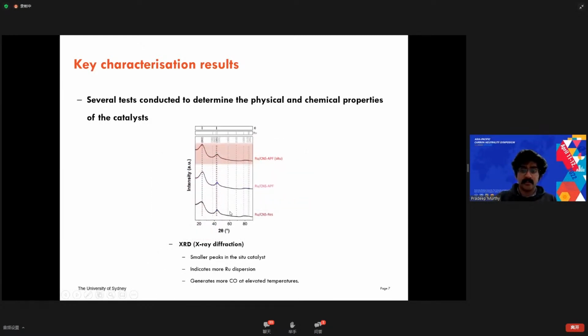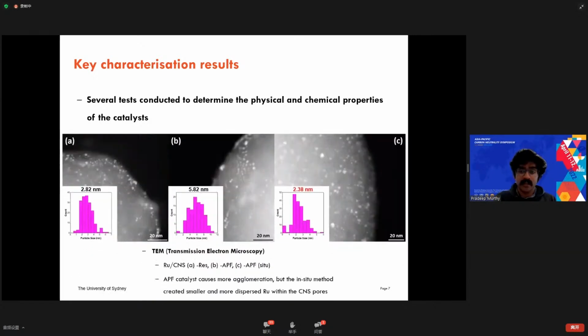An XRD revealed smaller peaks in the in-situ catalyst, which would indicate more ruthenium dispersion, and according to the literature would generate more carbon monoxide at elevated temperatures.